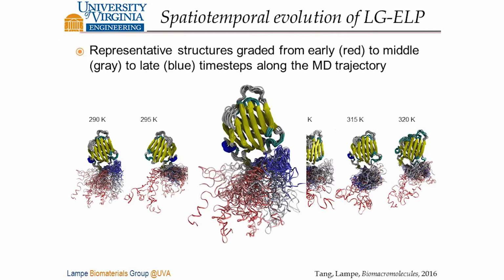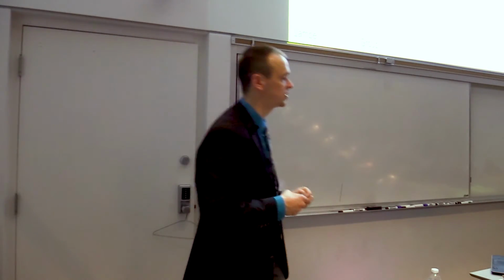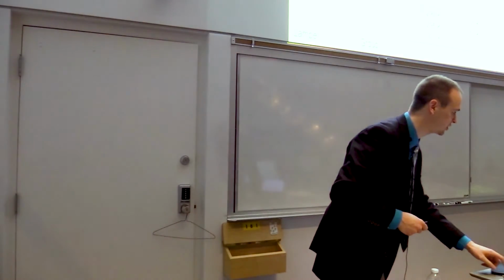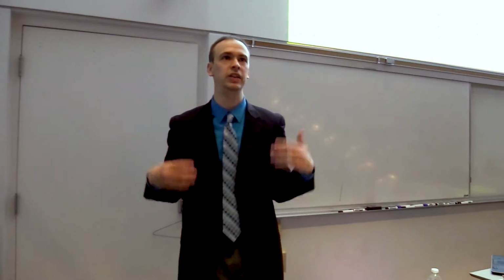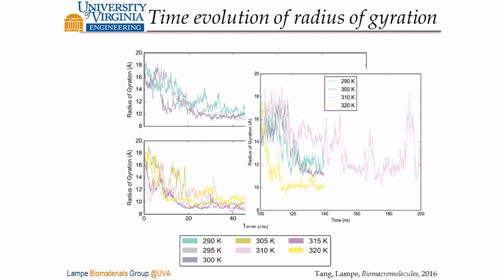At this property, that protein's probably becoming thermodynamically trapped because it's heated up so high, it gets stuck in this very tight structure. Whereas it takes a little longer here, but ultimately gets to something similar. And we looked at that general size by a thing called radius of gyration. You can measure basically the radius of how big that thing is. And that collapses in all cases pretty quickly, but it continues having some flexibility in some of these conditions.